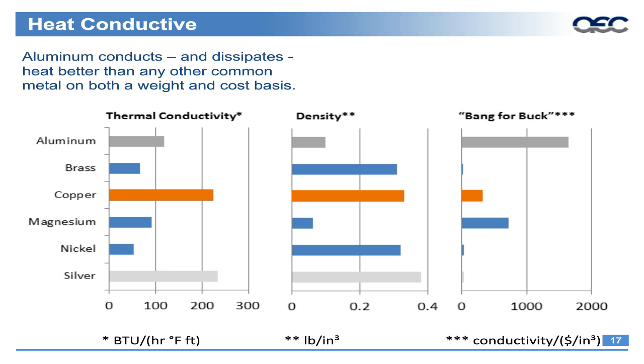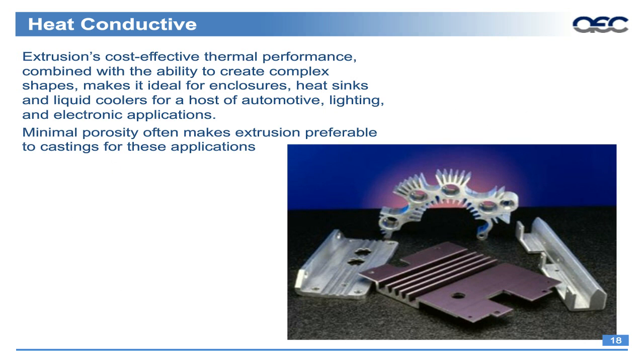The next graph is density, where you see silver is some of the highest density, but the only one that's really less dense than aluminum is magnesium. But then when you put basically the two together, you do more of a value calculation. The biggest bang for the buck actually comes in when you're using aluminum, because it has one of the lowest densities, plus is one of the better thermal conductors. And then bringing those features together, you actually have a very efficient thermal conductor, which is why you'll see aluminum extrusions used from LED lighting to heat sinks to cold plates to electrical enclosures, plus also other types of electrical bus conductors. So here again, with the relative ease of design and production of an aluminum extrusion, that's why you'll see it in all those various types of thermal products that I just mentioned.